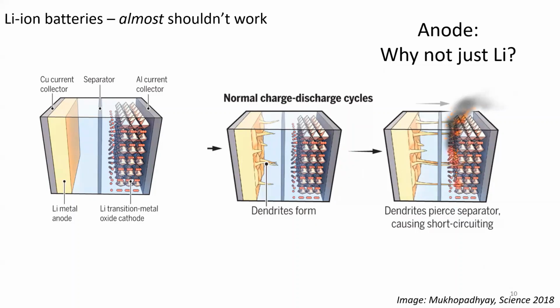Unfortunately, what does happen when you recharge a battery with a lithium anode is that the lithium atoms like to form these spiky crystals that we call dendrites. With enough recharge cycles, those dendrites grow and they reach across and they touch the cathode. At that instant, we have the anode, which has electrons that are really high in energy, touching the cathode, which is a material that has the possibility of a really low energy state for those electrons. And so all the electrons in the anode rush over to go join the cathode, which is a lower energy state. It releases a lot of energy really fast. It produces a bunch of heat, and it causes stuff in the battery to catch fire.